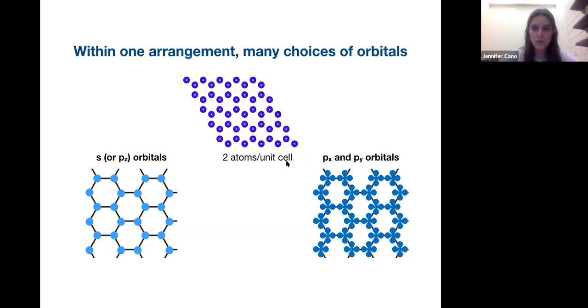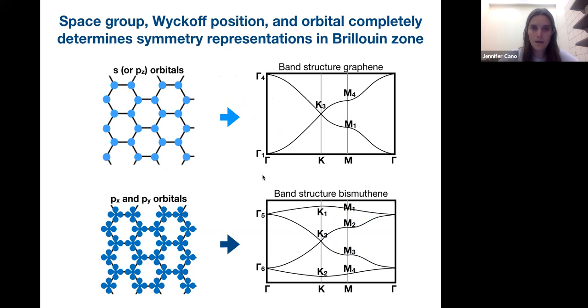So each different choice of orbital gives us a different atomic limit, or you can think of that as a different set of Wannier functions. And the consequence of this is that all of these symmetry attributes together, which is the space group, the atomic configuration, and the orbital content, that's all labeling symmetry in real space, and it completely determines the irreps that appear in momentum space. So for example, if I have s orbitals on the honeycomb lattice, which has the same symmetry as pz orbitals on the honeycomb lattice, I will always get this band structure.